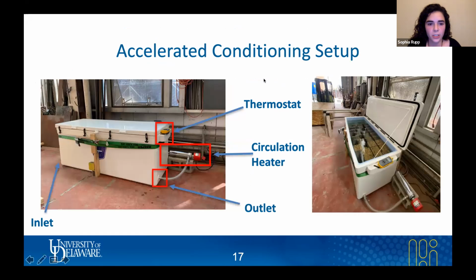This is the accelerated conditioning setup that my lab manager and I came up with so that we can follow the guidelines specified by ACI. It consists of a very large cooler that, as of right now, has all 33 of my ACP beams immersed inside it. There is an inlet and an outlet that is connected to a circulation heater and a pump. This keeps the water consistently circulating in and out of the tank and through the circulation heater to keep it at that specified temperature that ACI requires.